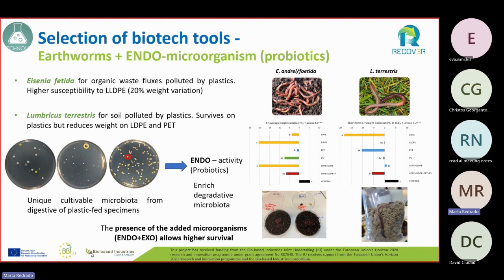In the case of earthworms, we did more or less the same with Eisenia fetida and Lumbricus terrestris. All of this is at lab conditions, right? Eisenia was capable of growing in organic waste polluted with plastic, but showed much higher susceptibility to the presence of polyethylene in comparison to the other polymers. Lumbricus terrestris survived well with plastic, but its weight was reduced when it grew with polyethylene or polyethylene terephthalate.